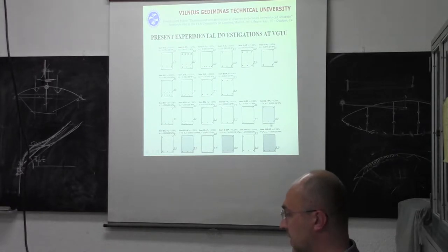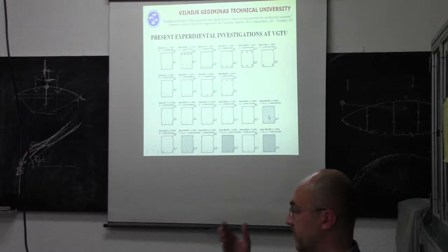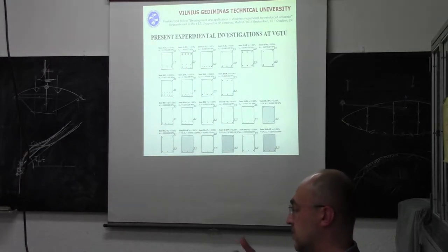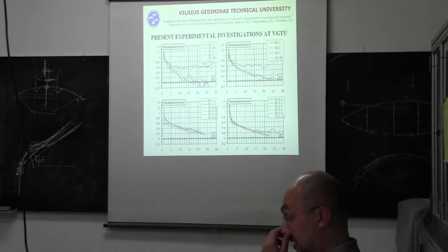Did the concrete have any fiber or not? No, some of the concrete specimens had a very small amount of fibers. This was our first try to use fiber reinforced concrete, and the maximum amount of fibers was 0.3. It was a very low amount of fiber to obtain some differences, but we obtained very obvious differences in the moment-stress state relationship for the beams with three layers of reinforcement.